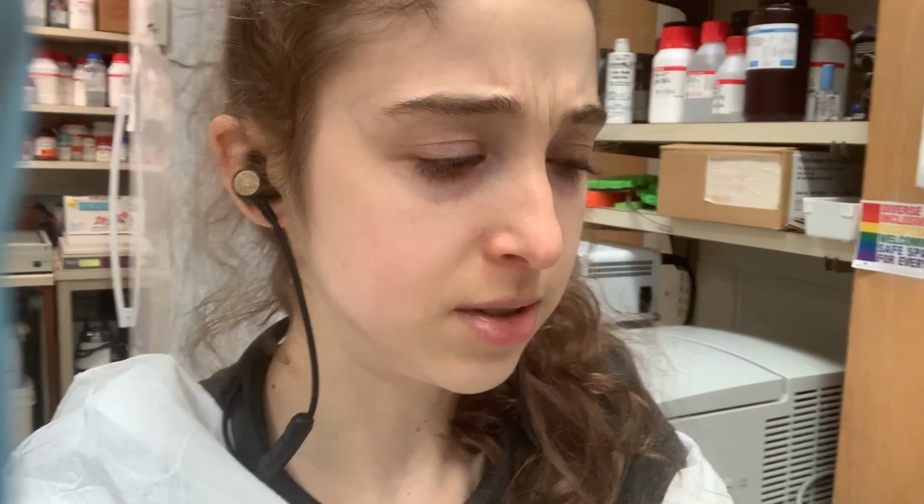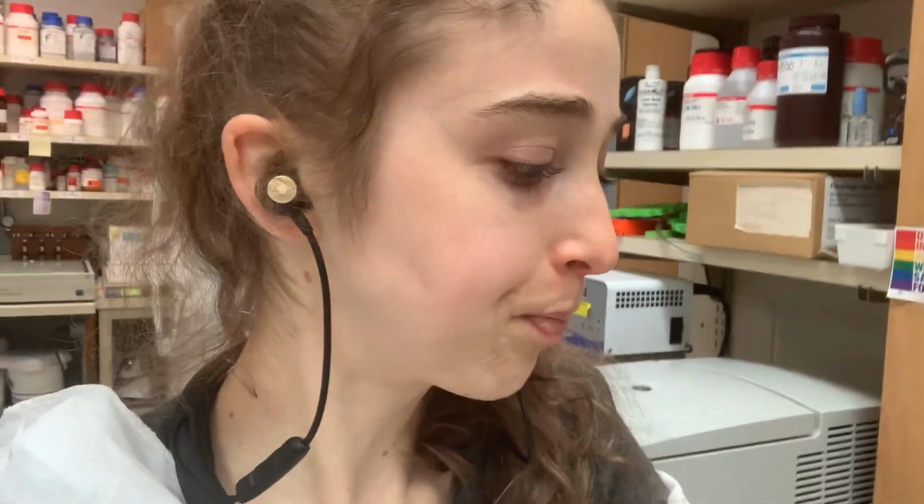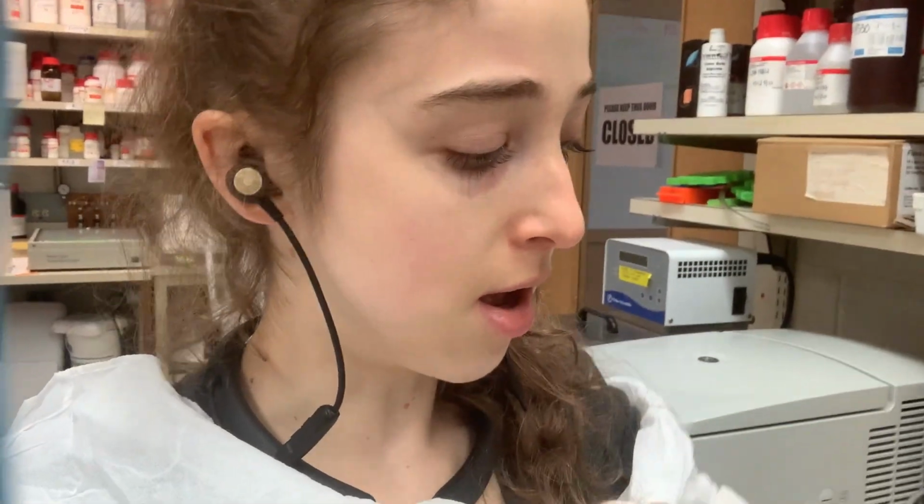Typically it takes somewhere between half an hour and an hour for each of the different sets to polymerize. You do the same type of thing for the stacking and the resolving gel. You add the polymerizing reagents right before you do the reaction, or else it'll harden while you're preparing. You want to add the 2 reagents, the APS and the TEMED, quickly after one another,